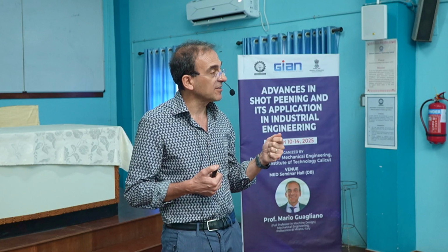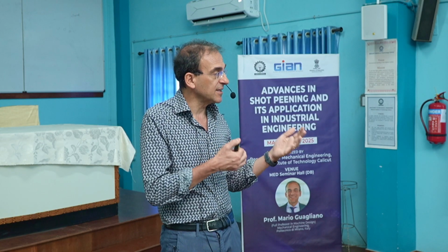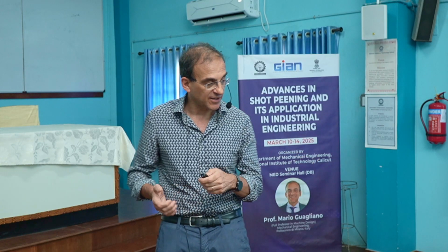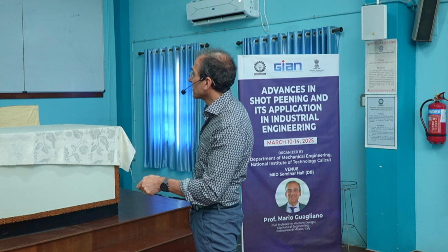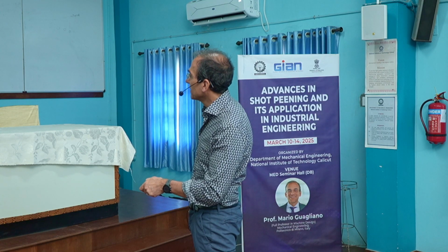This means that in this case we can also apply the traditional Haigh diagram, which is based on crack nucleation. And this is this part of the diagram. So this is a sketch. This is the part that continues here, the modified diagram, but we see that this refers to the original traditional Haigh diagram, and is more than the Fuchs one, and this is referred to crack initiation. If crack initiation does not happen, even propagation cannot start. And so the final trend is this.